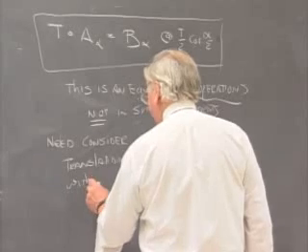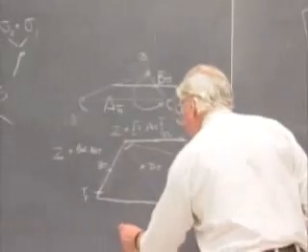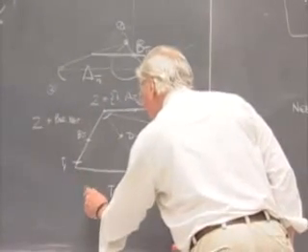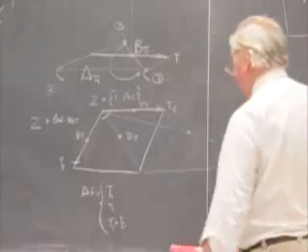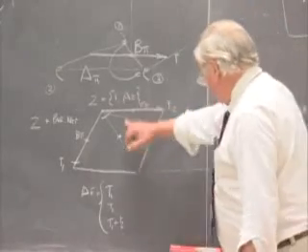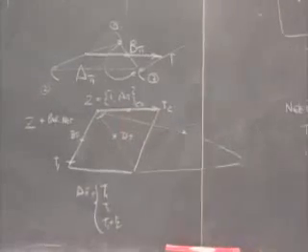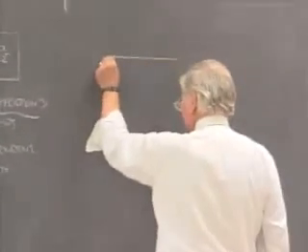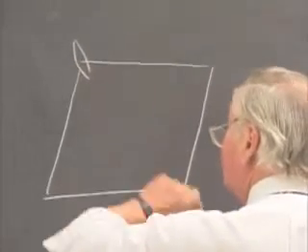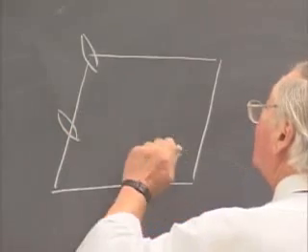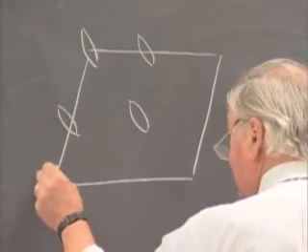And that means for the addition of a twofold axis, I need do only what I have, in fact, just done. I want to consider a pi with T1, T2, and T1 plus T2. If I have the operation a pi or b pi or c pi or d pi at these 4 locations, that is all I need have present to say that I have, in addition to the twofold axis that I added to the lattice point, a twofold axis halfway along T1, a twofold axis halfway along T2, and another one smack in the middle of the cell.